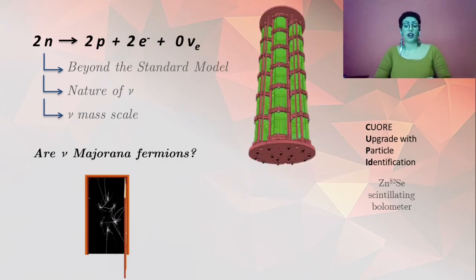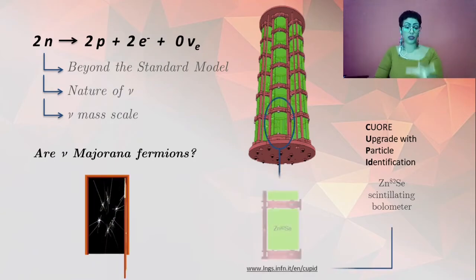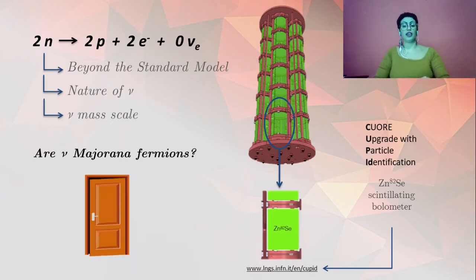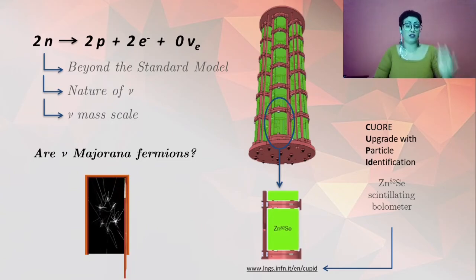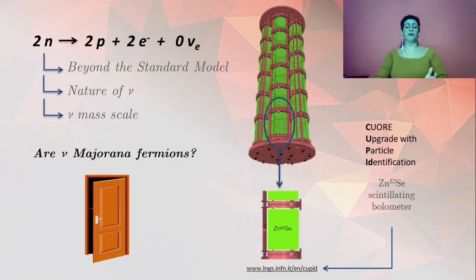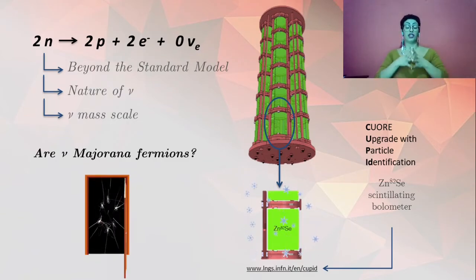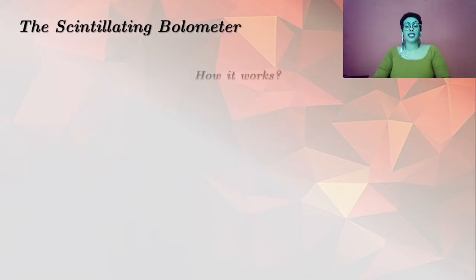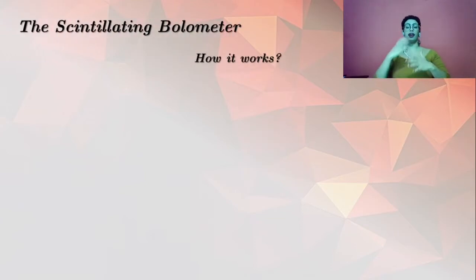The modules are arranged in a tower-like structure, where each module consists of a luminescent cylindrical zinc selenide crystal coupled to thermistors and a thin film of germanium deposited on its surface for light detection. The entire system is kept refrigerated at a controlled cryogenic temperature of the order of millikelvins. The scintillating bolometric technique is capable of reading simultaneously a heat and a light pulse produced by the material due to an interaction with a particle or radiation.